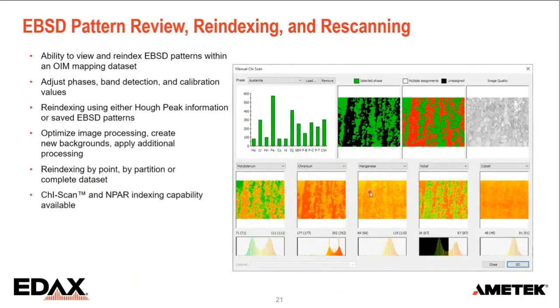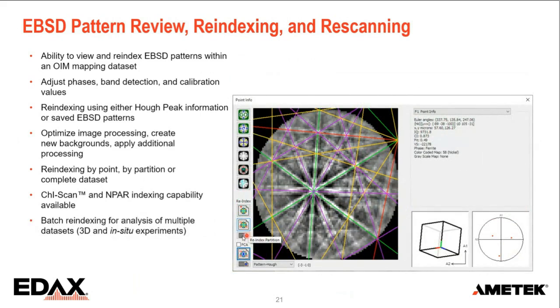You can, of course, combine that with chemical information. So here you can just select, based on an element or multiple elements, which points you want to assign to a certain phase. If they may not be distinguishable by EBSD alone, you can use the chemistry. And you can even do that in batches. So take a whole sequence of partitions for re-indexing or re-indexing with chemistry. So it's a very, very powerful tool to help you maximize the indexing performance of the system.